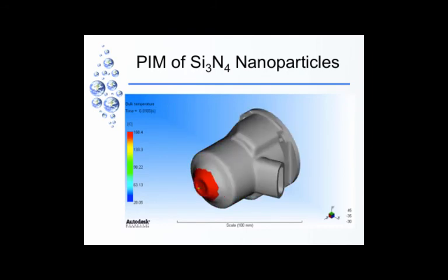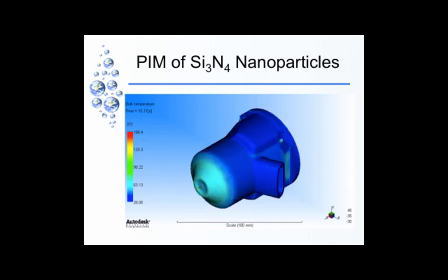So those are some kinds of properties that we measured to be able to, again, like we showed some examples for microchannel structures. Use that for showing this. We have now gone to the stage where we can now build die cavities after looking at different configurations of part design and so on. And now we also have gone ahead and looked to make sure that the mix that we have created can be sintered successfully and get good properties. We have quantified what the shrinkage is, and now we can make an oversized mold to be able to make a component like this.